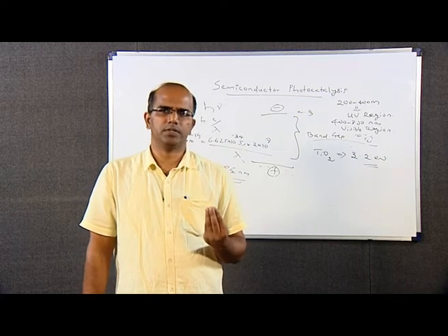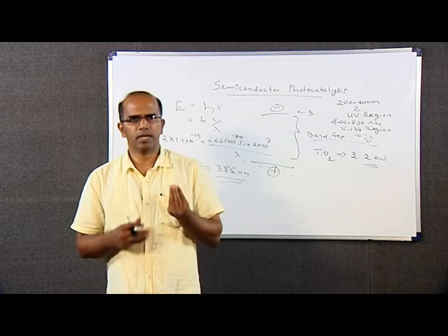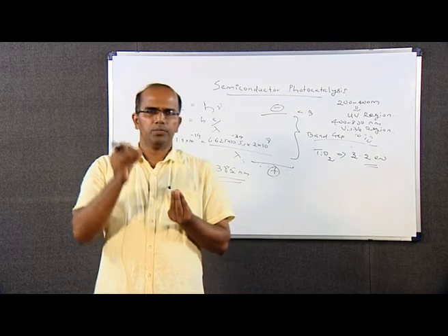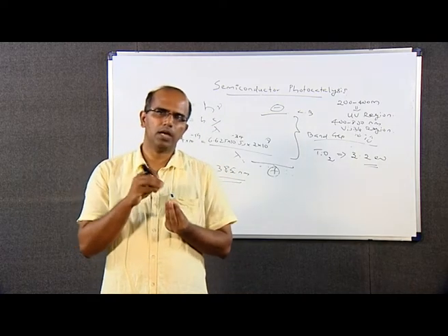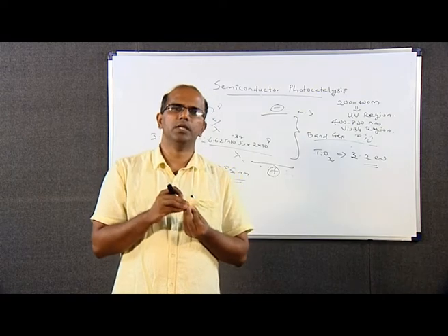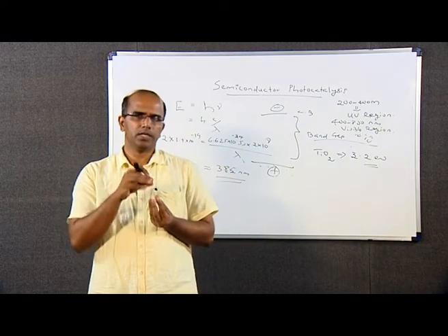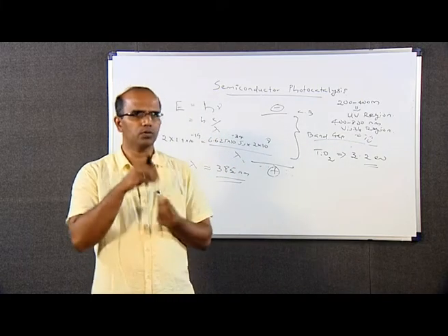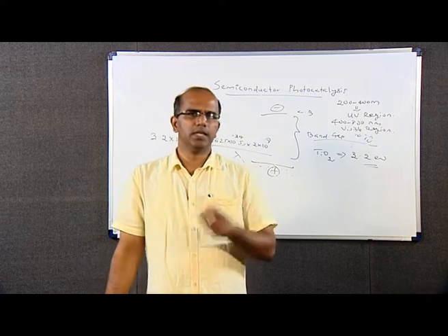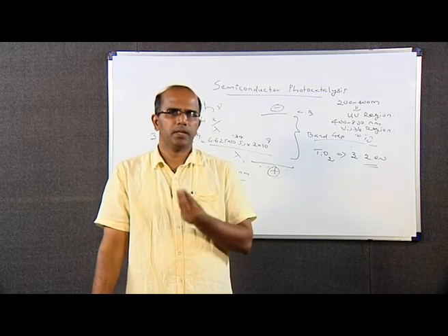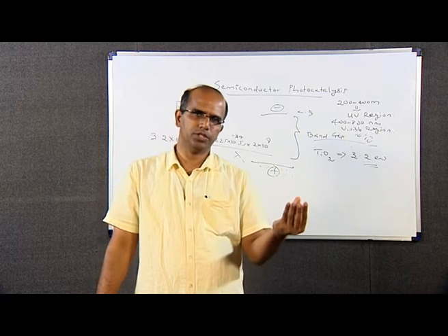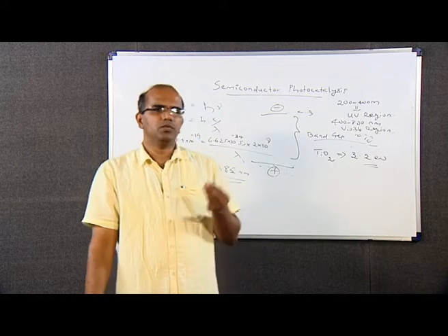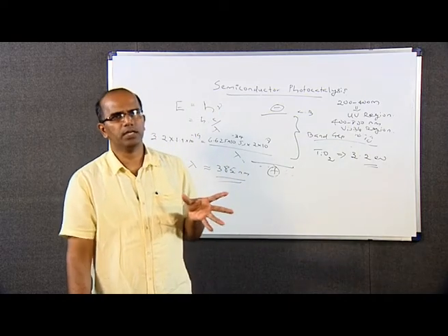Or suppose you are taking this type of semiconducting nanomaterial in a beaker and putting some pollutant or colored organic compound, for example methylene blue, rhodamine, etc. You take that in a beaker and put some semiconducting nanomaterial like TiO2, and you take that solution plus the nanomaterial into a UV chamber and treat it for 10 to 15 minutes. Then the UV light falls upon the semiconducting oxide.